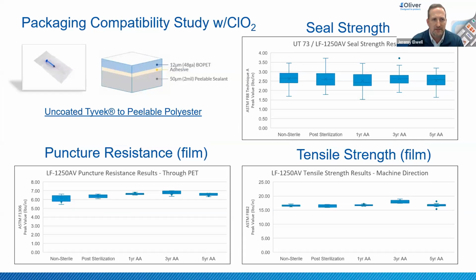And just repeating this on the further slides, this is basically the same approach. This is just a peelable polyester sealed to uncoated Tyvek. So everything's the same, but in the diagram, you can see that the nylon from the previous slide is replaced by polyester in this film structure. So nylon, polyester, both showing the compatibility through seal strength, puncture resistance, and tensile strength of the film.